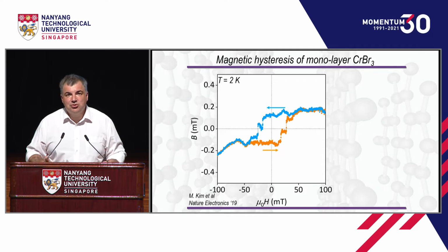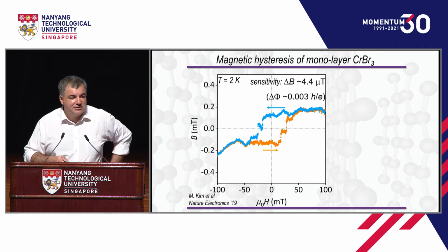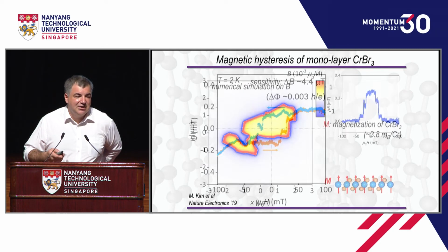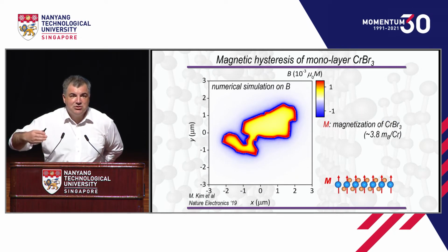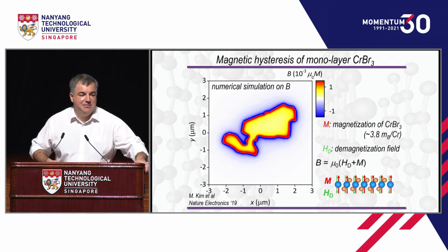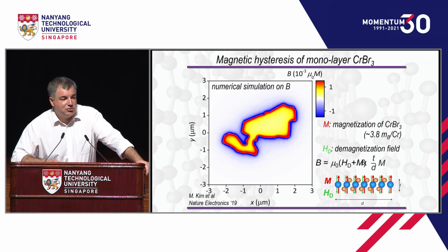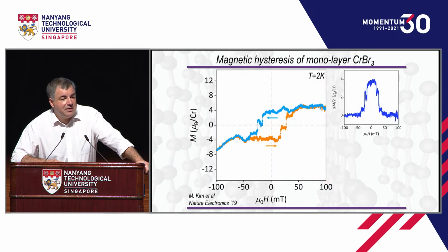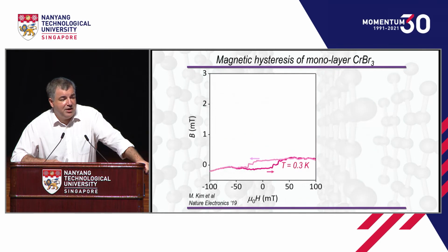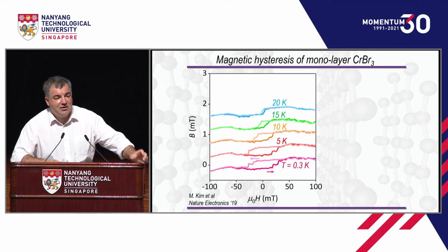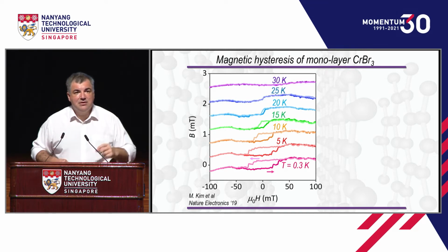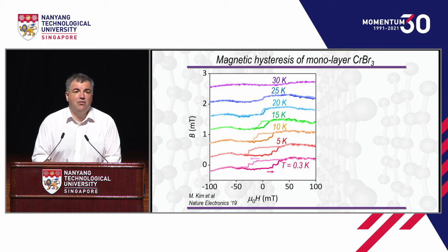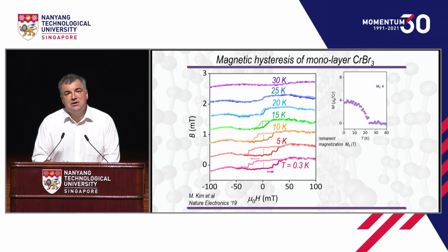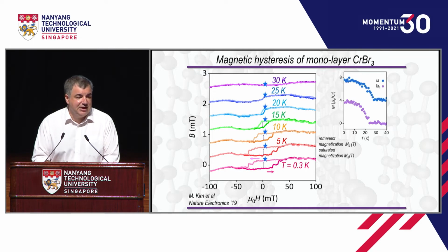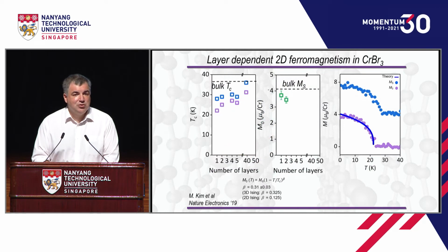So you see the usual hysteresis loop for the ferromagnets, and those individual steps which you see. It's basically the domain wall moving from one position to another, getting pinned and depinned, and then we can recalculate it into the magnetization. So then if you do it for many different temperatures, you can just extract this magnetization, and you can extract the magnetic moment of your material, and that's exactly what Yang predicted in his paper, and we tried to do exactly that.